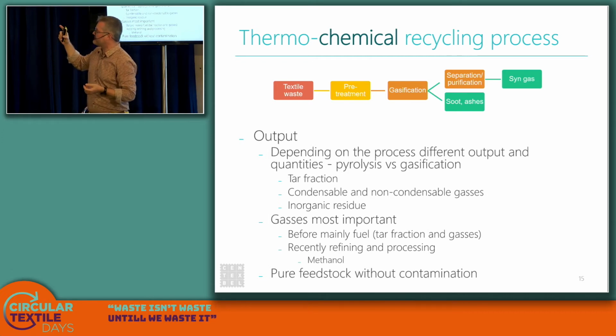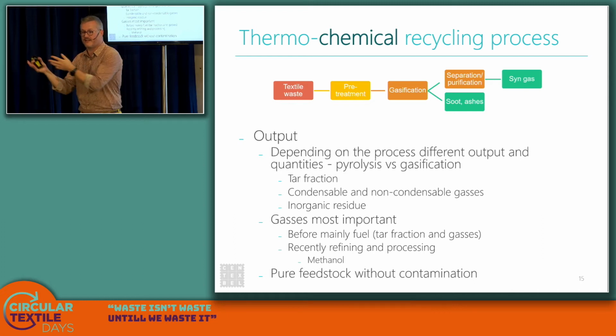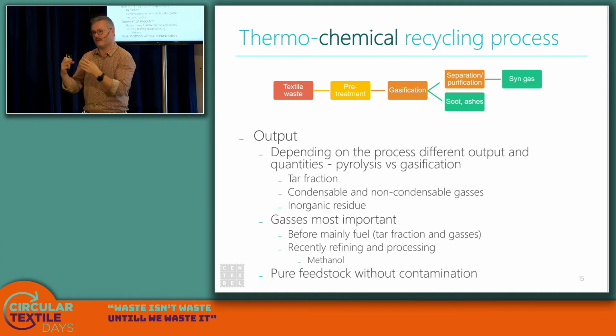The difference with gasification is that you heat up at a higher temperature, 1000 degrees more or less, and then you will burn everything. You don't have that tar fraction, but everything goes up into gases, which are then used as a feedstock. So they can refine those gases within existing processes in order to get feedstocks for the chemical industry. And depending on what they do, you get different feedstocks. So in the atmosphere of oxygen or other gases, you get other feedstocks. So there are a lot of possibilities, and they think they have more or less 70% of your material is recovered with gasification, which is quite a high yield.